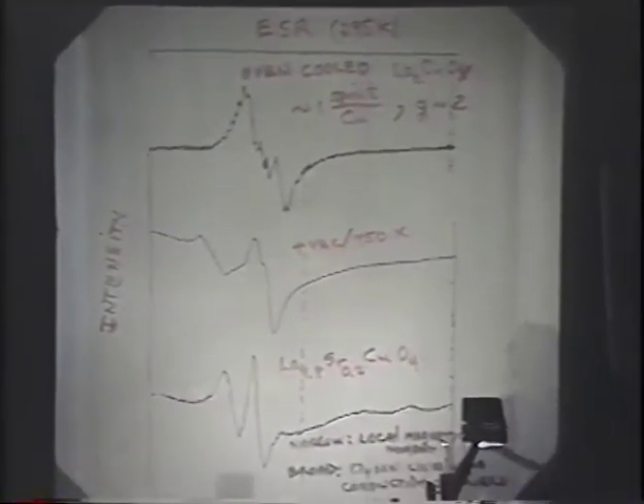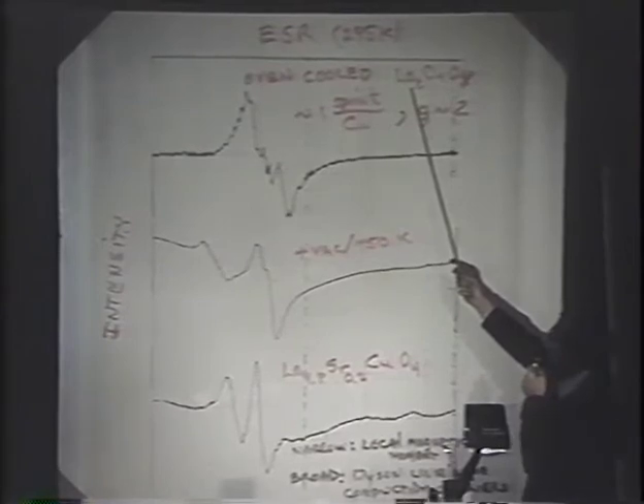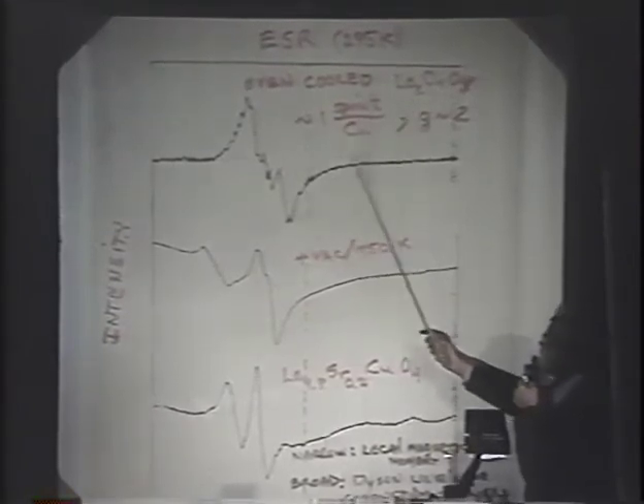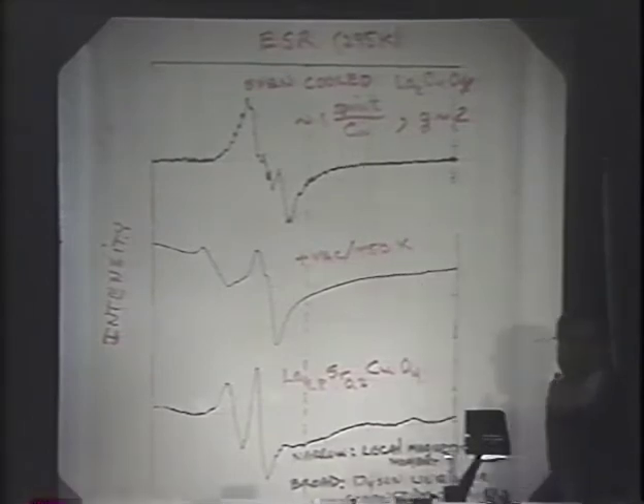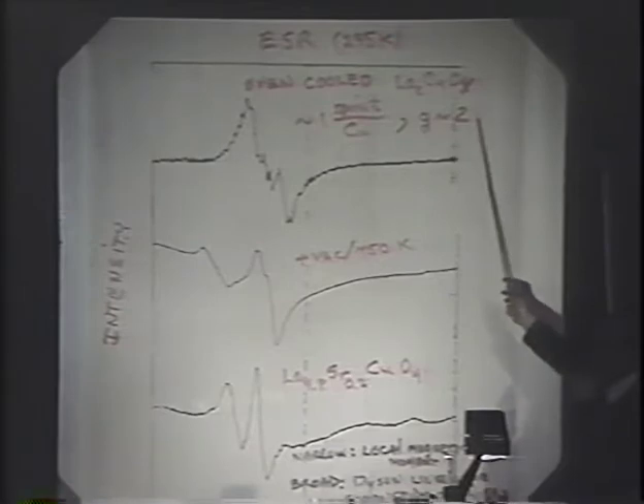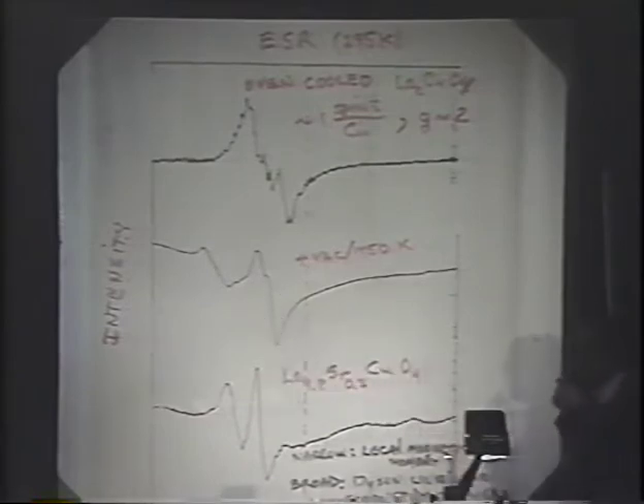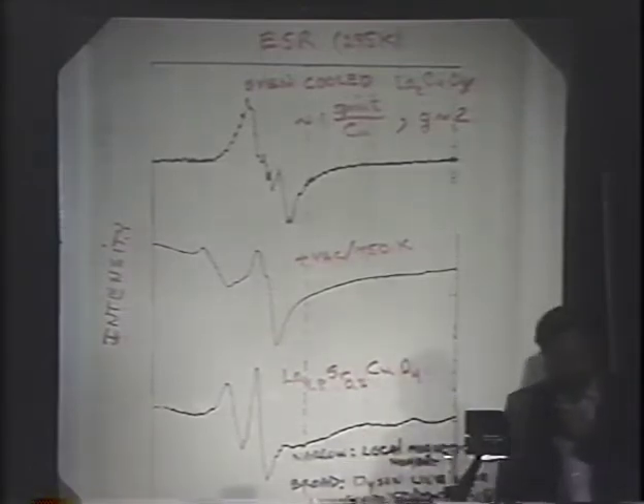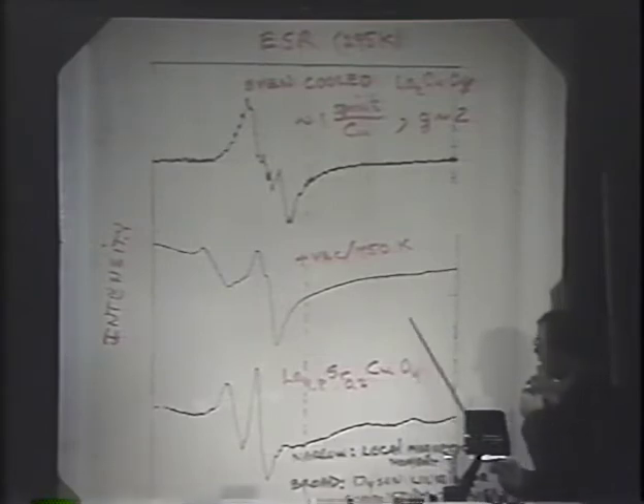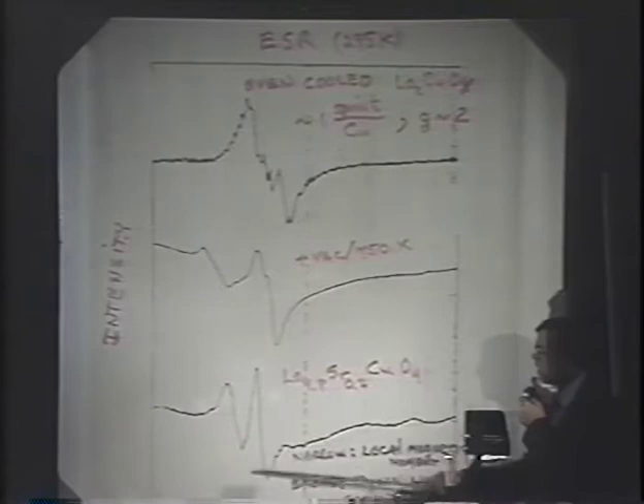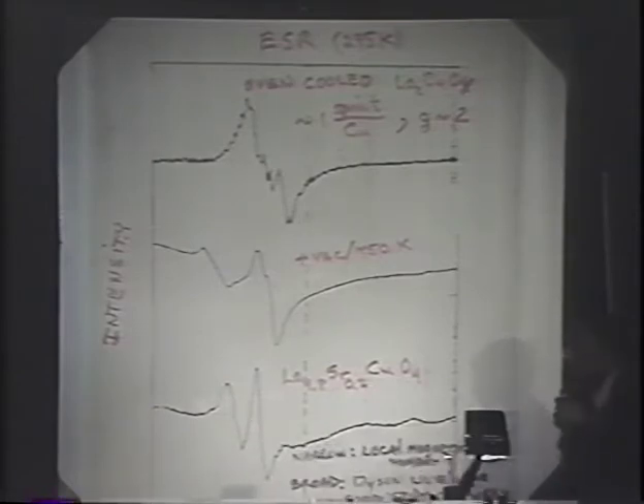It might be surprising, but one can get quite a strong electron spin resonance signal out of these materials. This is an oven-cooled La2CuO4. The intensity after a double integration of the spectrum gives approximately 1.5 spin per copper with a g of about 2. Under vacuum at 750, which turns it into an insulator, you get this kind of spectrum. It's a little bit different. And when you dope it with strontium, you get a different signal, but the point I'd like to make is that it appears to be a superposition of a local magnetic moment and a broad Dysonian peak due to the conduction electrons.